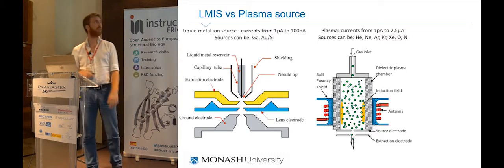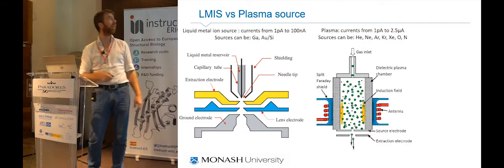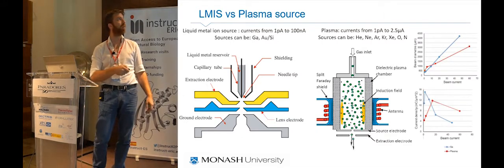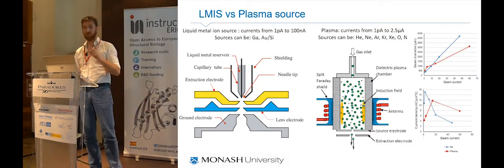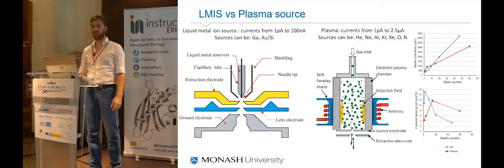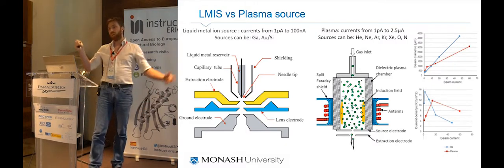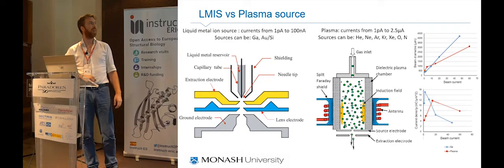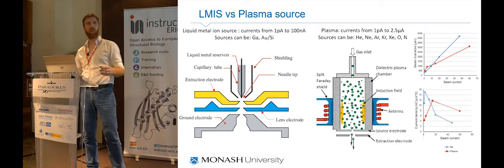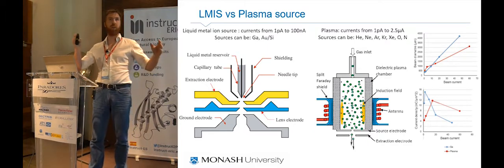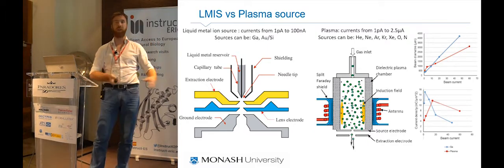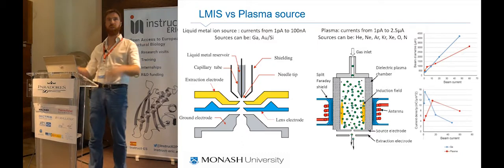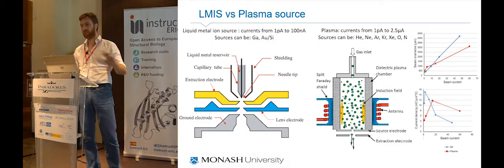So the main advantage is you can get currents which are in the order of 2.5 microamps, not nanoamps, like in this liquid metal ion source. These are measurements that we've taken between different instruments, and the take-home message is, if you need to work anywhere between 1 picoamp and 10 nanoamps, buy a liquid metal ion source. If you want to work beyond 10 nanoamps, buy a plasma FIB.